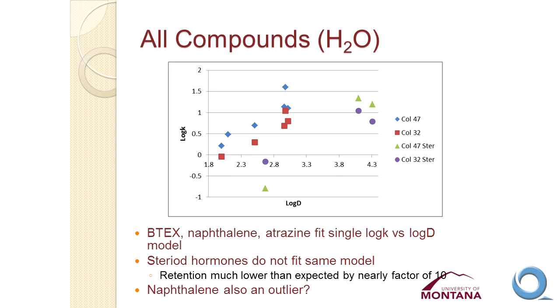If we take all of the aqueous data that we have for the different compounds, and we plot, again, the logarithm of the retention factor versus the logarithm of the octanol water distribution coefficient, we see for column 47 a nice linear region up here. For column 32, a nice linear region. But then, if we try to put the steroid hormones on that same plot, they fall well outside the model or the relationship. So these compounds are giving much lower retention than what we would expect from this hydrophobic interaction mechanism. We don't know why yet. We just know that that's the case.